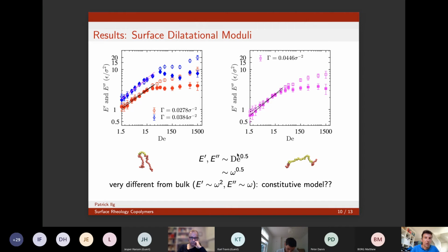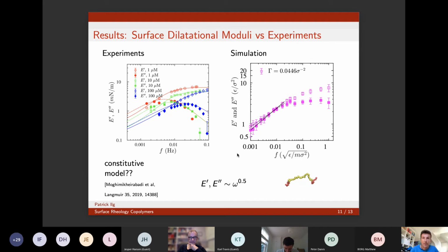I mean, this is first of all very different from what we are used to from bulk polymers, which go linear and quadratically. And so, of course, we would like to have something like a Maxwell model or a simple constitutive model describing that. For the experts, there is, in fact, a constitutive model claiming a square root of frequency dependence here. That is Lucassen and Van den Tempel. But the thing is that they have a completely different mechanism that is absent in our simulation. So we can have an apparent coincidence, but for the wrong reason, let's say. If we try to compare to the experiments, well, this is semi-quantitative. Unfortunately, it was not possible to go down in frequency as much as we thought.